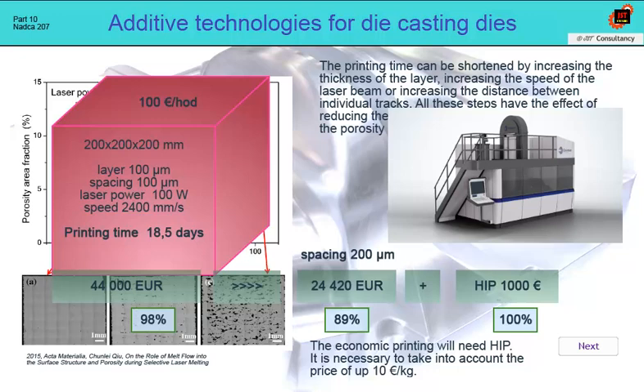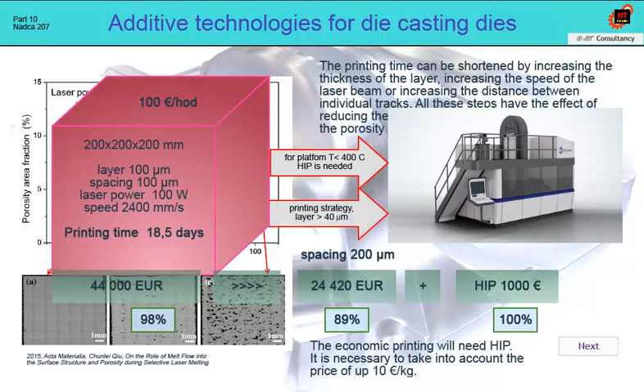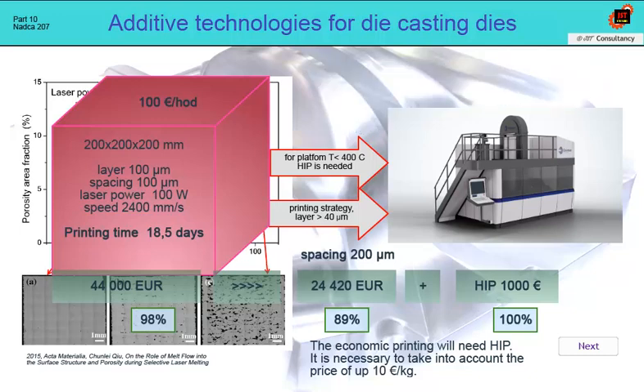It is a question of what criteria to set for the use of HIP technology, when yes and when not. We do not know the relationship between the toughness of the material, resistance to thermal fatigue, and porosity. But since porosity represents random defects that we cannot recognize from a macroscopic point of view, hot isostatic pressing significantly increases our certainty that these random defects will be removed. At the same time, it allows us to print with significantly lower density, which means cheaper. Therefore, if printed parts are to have the same service life as parts made of forged material, hot isostatic pressing technology should always be used.